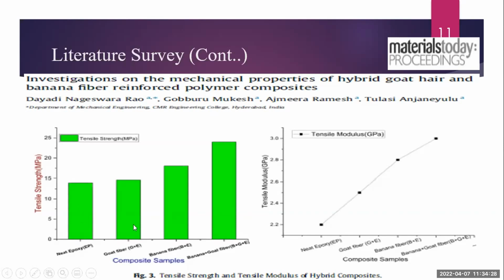If goat hair is mixed with the epoxy, the tensile strength increases slightly. If banana fibers are mixed with the epoxy, again the tensile strength increases. But if banana fiber and goat fiber are mixed with the epoxy, you can see that it gives the highest tensile strength compared to the other mixing ratios. It means we can think that if hair is mixed with plant-based fibers, then we can also increase the tensile strength. The tensile modulus also shows the same result as the tensile strength. Here also the banana fiber, goat fiber and epoxy combination gives the best result compared to the other mixing ratios of other fibers.